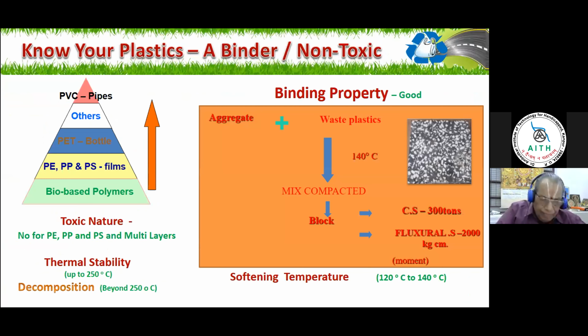So see here, what I do is take the stone, heat it to 170 degrees. Take the plastic, your carry bag, polyethylene or polypropylene, cut it into small pieces, 2 mm to 4 mm. I can even show that here. If you are interested, you can see. I have kept it on my hand. This is the plastic which I use. We just cut it into 2 mm to 4 mm.